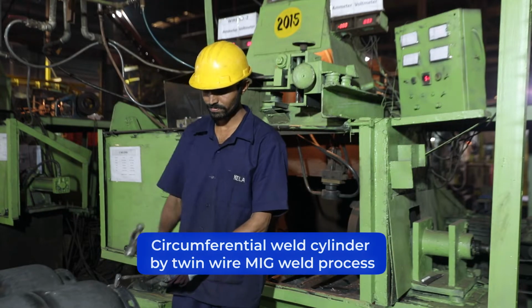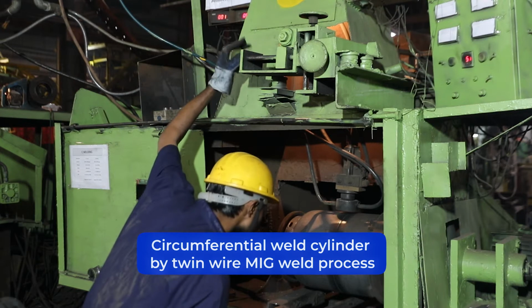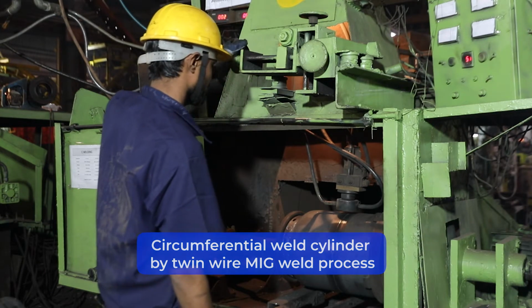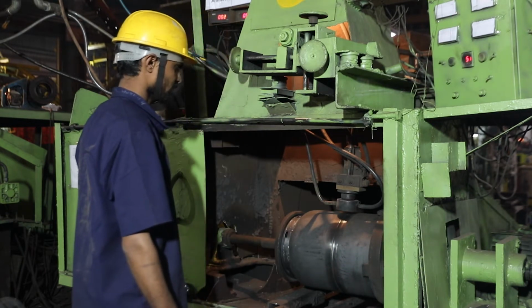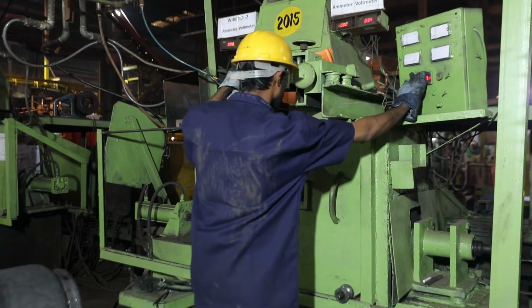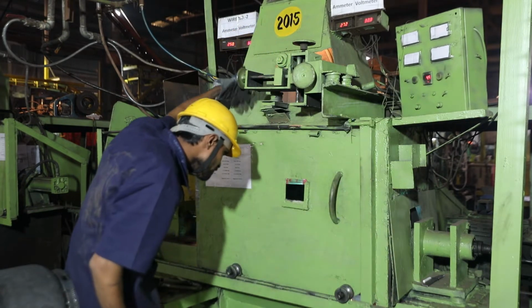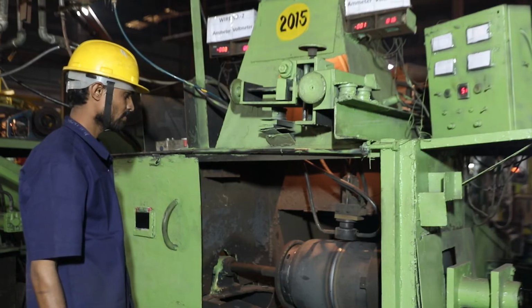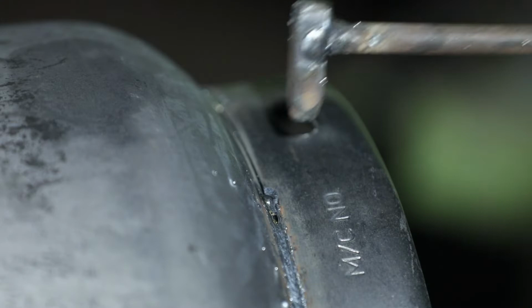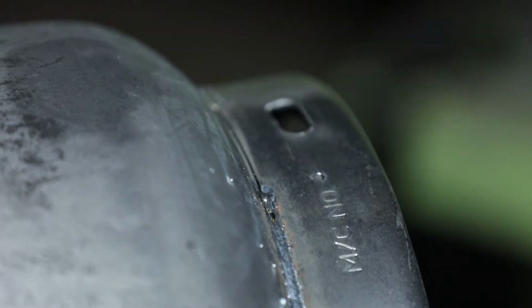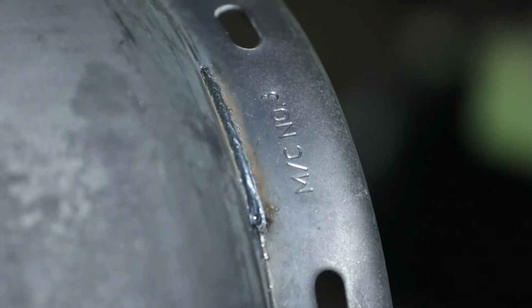For the circumferential welding of the cylinder by twin wire MIG welding process, the current, voltage and revolution time of circumferential welding need to be as per requirement. Diameter of the CCMS wire should be 1.2 millimeters. Machine number will be punched on the foot ring of each cylinder for identification.